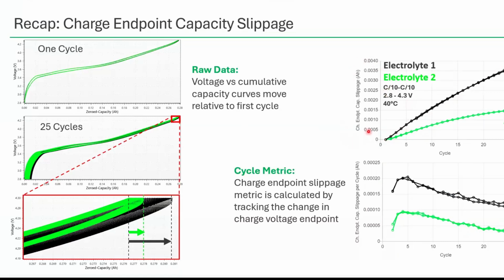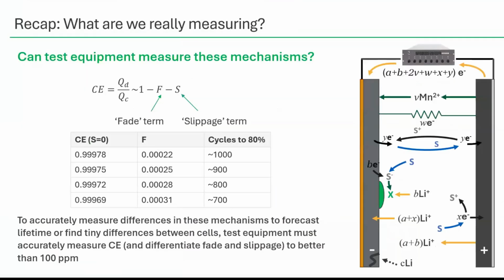We can also look at this metric as charge endpoint capacity slippage per cycle, which is more like the rate at which these reactions are happening. Again, electrolyte 1 has a much higher rate of these mechanisms than electrolyte 2. This gives us very quantitative insights into things that we can't really see with other types of cycling equipment.